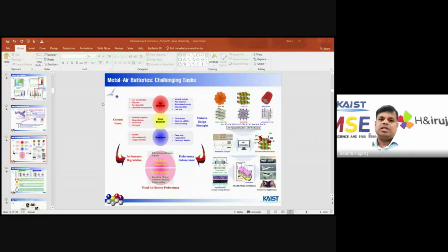Another thing, what is the current issue for metal electrodes like lithium or zinc or whatever metal anode? Dendrite formation. Because when we use the metal in direct contact with the electrolyte, dendrite formation happens and the shape changes. Because of the dendrites, it may be highly corroded, then the shape will change, and passivation will be one of the issues. This kind of issue may be overcome by our new strategy. We are making 3D-based electrode materials to overcome this.